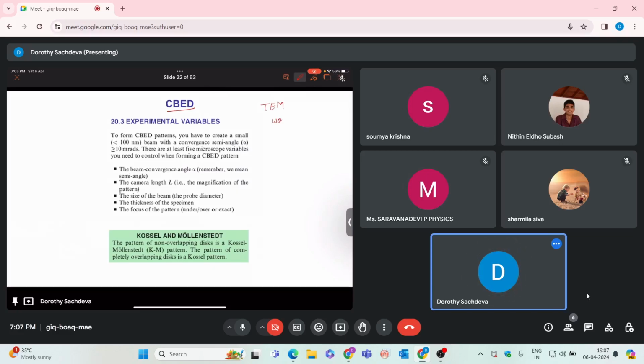TEM works in parallel beam mode. Remember, if this is your specimen, then your incident beam should be almost parallel. But CBED is convergent beam electron diffraction. So there you need to converge your beam and then it should fall on the specimen, and then each diffraction spot will consist of the Kikuchi lines, and that will tell you a lot more information about the specimen orientation and all.